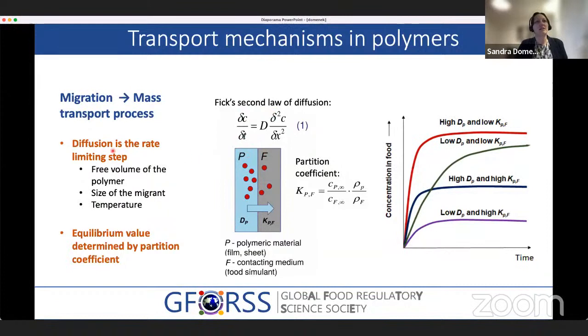This law tells us that diffusion is, in our field of application, always the rate limiting step. Diffusion is the kinetics, so the rate by which the transport is going to happen, and this is linked to the cohesiveness of the polymer, the size of the migrant, and the temperature. But then you also have a second part, which is the partition coefficient, and the partition coefficient, which is termed here, is describing the equilibrium value.